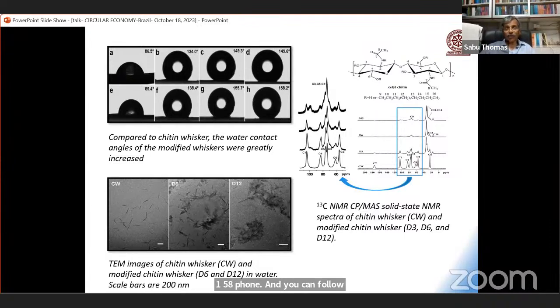And you can follow the reaction between bromohexadecane and nanochitin by NMR spectroscopy. And you can see these TEM images of the nanochitin and the modified whisker with the bromohexadecane. You might ask, what could be the utility of this material? This is an excellent additive for oil, because it controls the viscosity of the oil. So this is a beautiful additive for modifying the properties of hydrophobic oil.